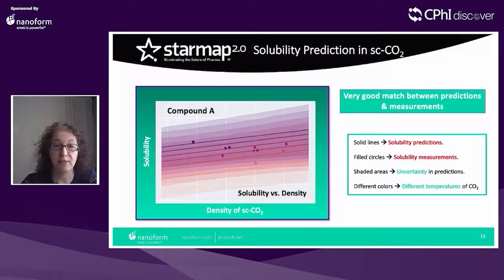And in terms of the capabilities of Starmap, they are shown here. So for this compound A, I'm showing the solubility in supercritical CO2 as a function of the density of the supercritical CO2. And density is one of the key parameters determining solubility. You can see here some solid lines which represent the predictions from Starmap, the filled circles that are representing the measurements that we performed in-house, some shaded areas which represent the uncertainties in the prediction, and the different colors are because we tested different temperatures. And you can see the proximity between the circles and the lines, which indicates that there is a very good match between the predictions and the measurements.